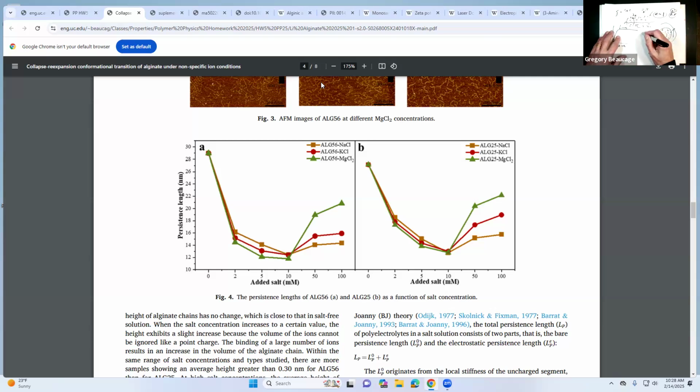If I put a big field on this, then it's going to move. It's still got a negative charge. It's going to move towards the positive charge, and the drag coefficient is going to follow Stokes' law by the hydrodynamic radius, and the force pulling it is this electric field that you put on it, and that's going to equal the velocity times the friction factor.